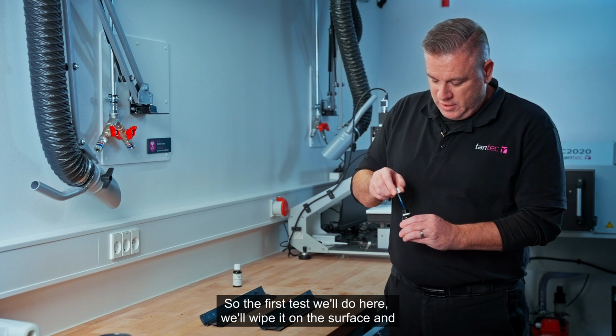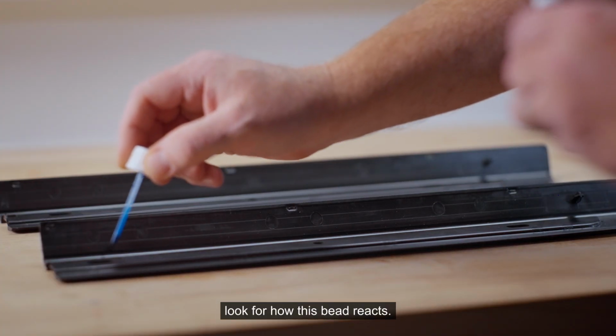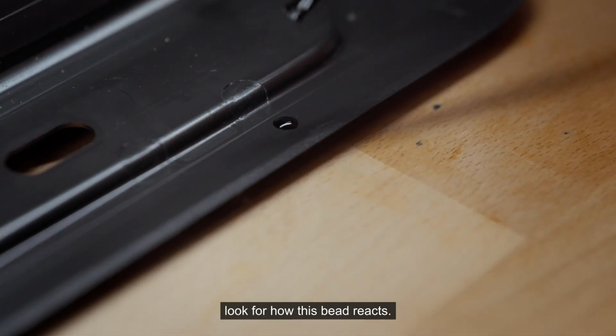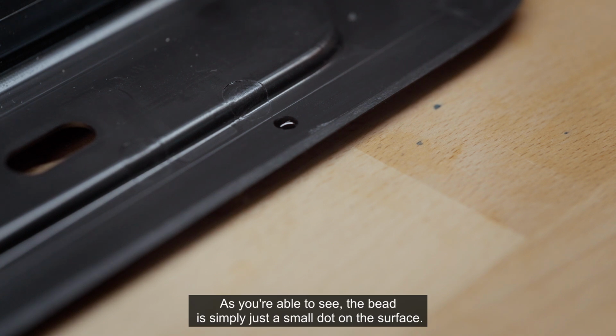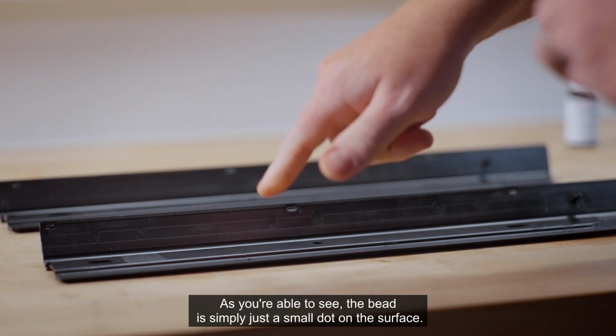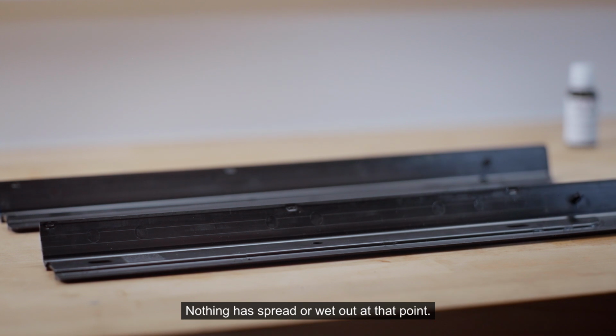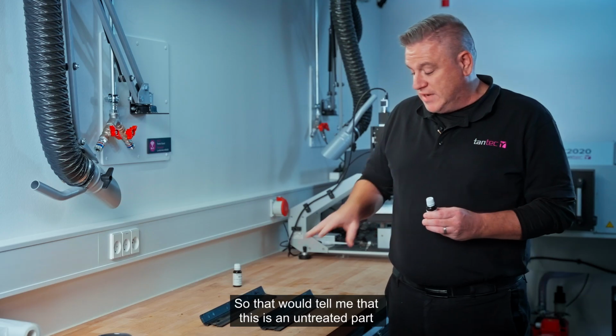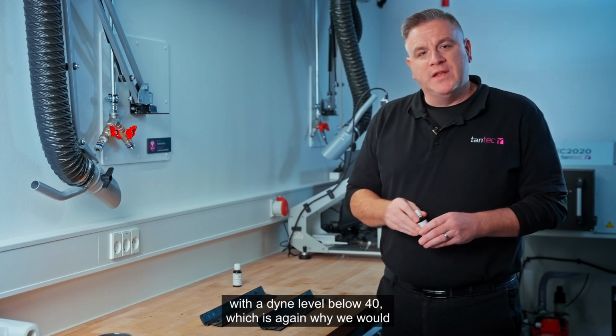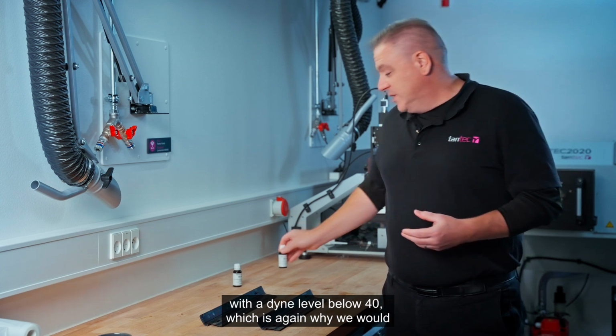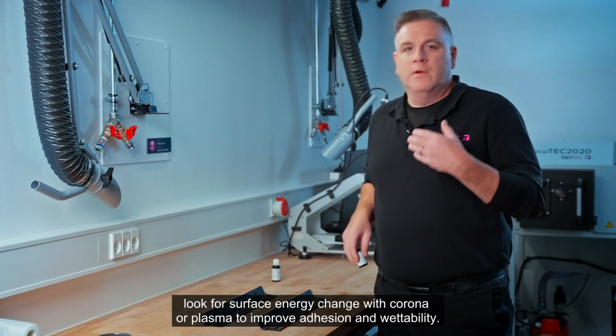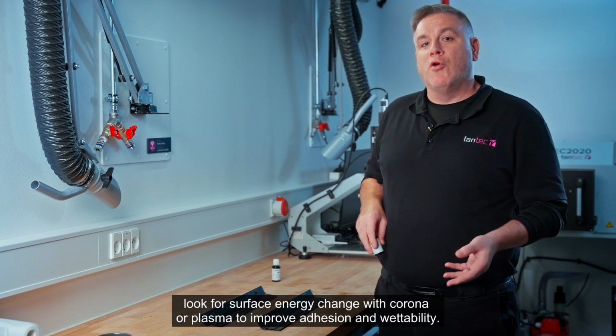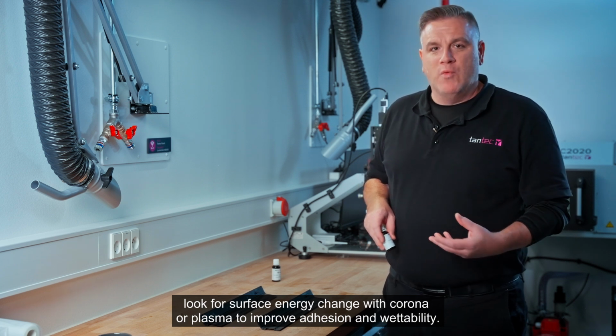So the first test we'll do here, we'll wipe it on the surface and look for how this bead reacts. As you're able to see, the bead is simply just a small dot on the surface. Nothing has spread or wet out at that point. So that would tell me that this is an untreated part with a dyne level below 40, which is again why we would look for surface energy change with corona or plasma to improve adhesion and wettability.